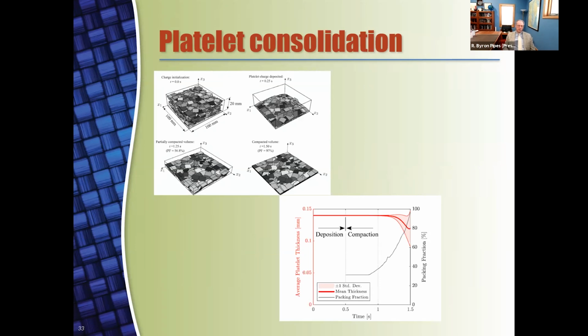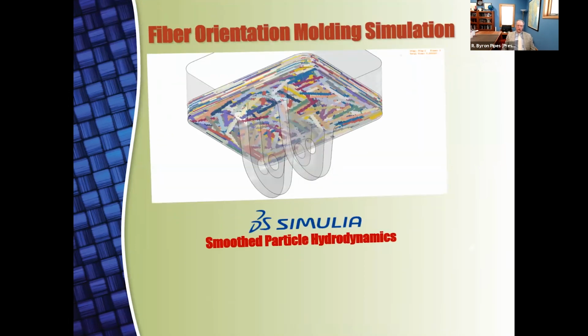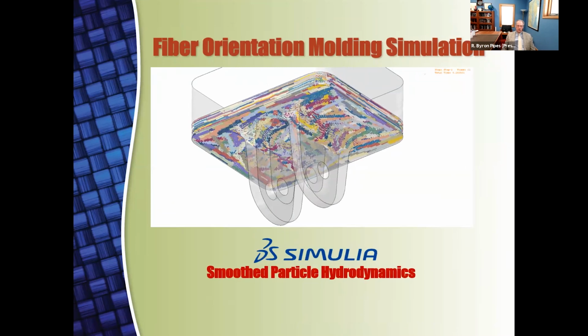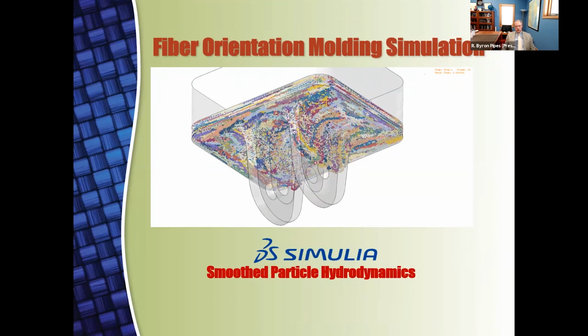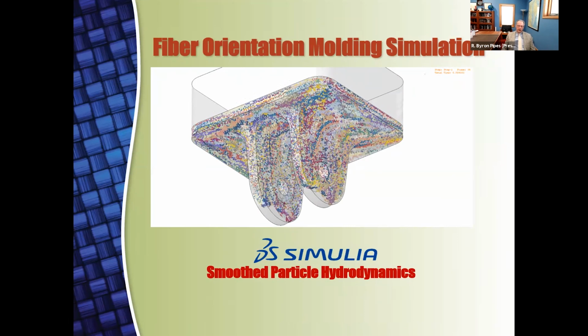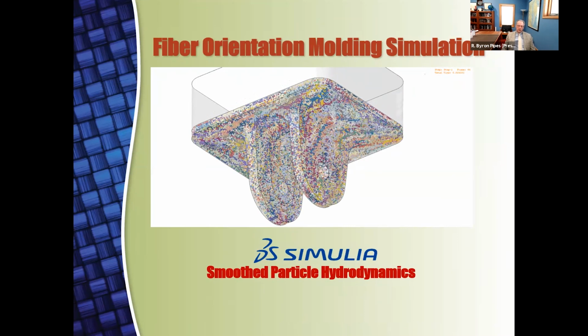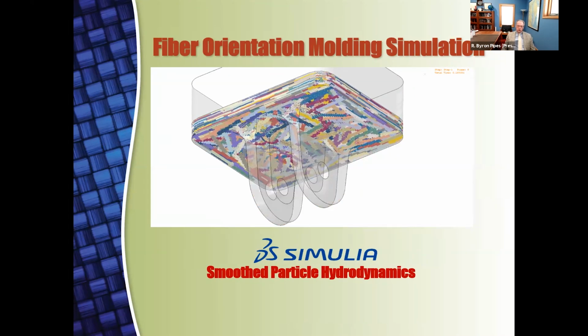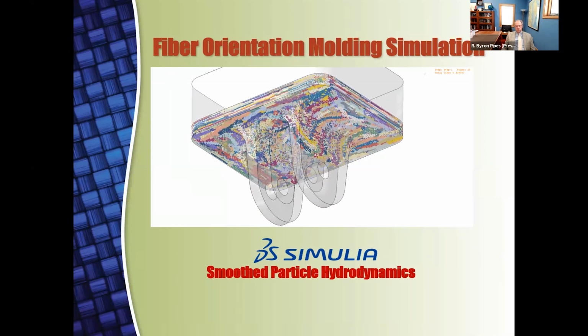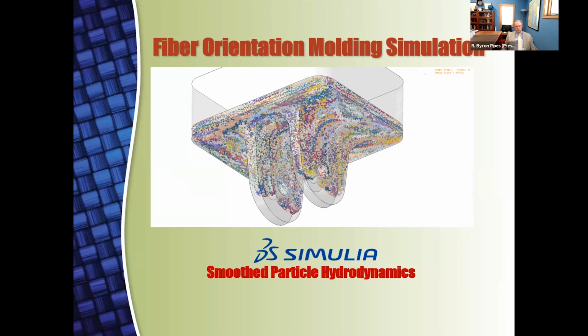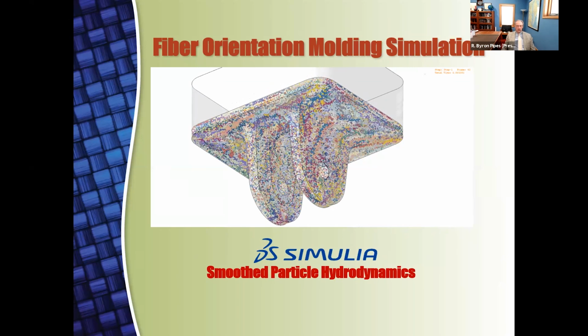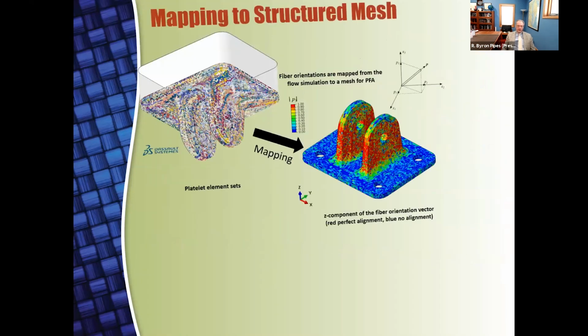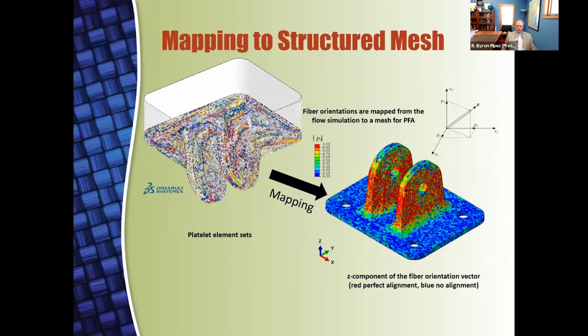This preform then enters the mold, and we carry out a molding simulation for the pin bracket geometry. What you see here are molding results for the pin bracket, in which we have the prepreg platelet material. It is squeezed, if you will, at the molten state and pushed into the mold. And this simulation is based in the Simulia product with a smooth particle hydrodynamic formulation and finite element methods. Next, this orientation state is mapped into the solid model for the performance characteristics.